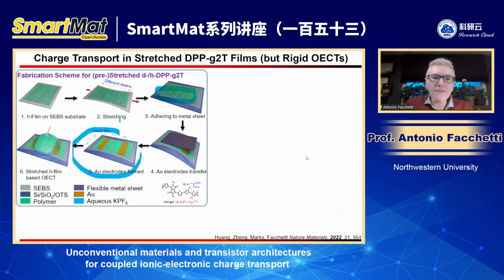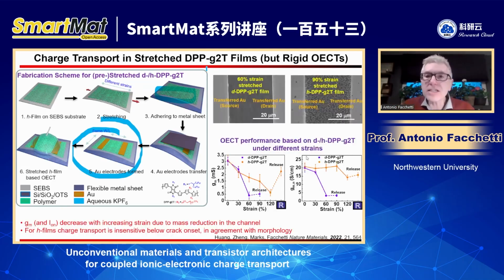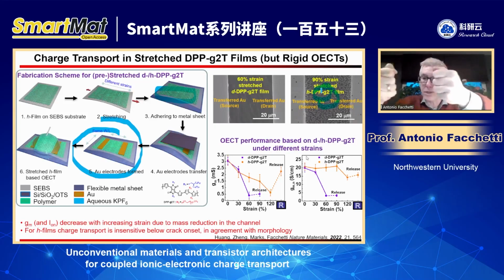In this way, you have devices where you have stretched the film at different degrees, but the W/L remains the same. So there is no variation in the quality of the contact. This is very important to study the charge transport independently of the stretch. And when you do this, these are examples of the device with dense film stretched at 60% and then laminated. And this is the second one here, the honeycomb film stretched at 90% and then laminated.